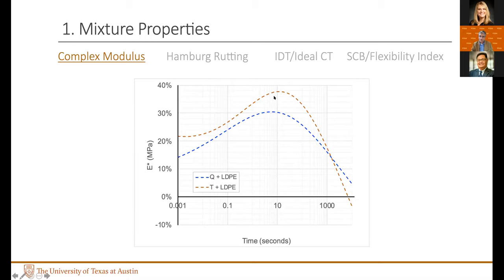So if you look at that, you'll notice that the change in stiffness also is not uniform, but you see the highest effect of that change in stiffness somewhere around these intermediate to high temperatures or moderate to high loading times. And then it drops off to no change. This makes sense because if you have very long loading times and or very high temperatures, at that point, the material is not contributing much. The soft nature of the binder will dictate the overall mixture performance and the aggregate matrix.